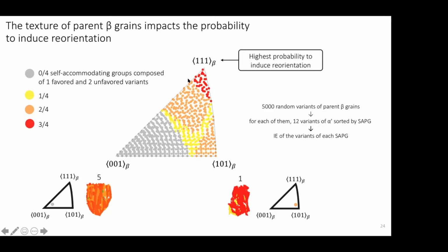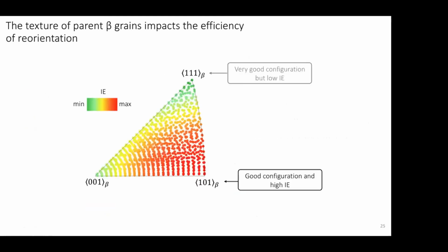So we know now that the occurrence of reorientation depends on the texture of the beta grains. And we know that close to 111, we have the highest probability to induce reorientation, but we also have to take into account another piece of data, which is the value of the interaction energy. Even if we have the highest probability to induce reorientation close to 111, we have in fact a very low value of the interaction energy. And if we have a low interaction energy, as I said, your variant will not give a lot of energy in the tensile direction, so it will not give a lot of deformation in the tensile direction. We can see it a bit like the efficiency of the reorientation. So you have a high probability to have reorientation, but it will not be very efficient. By contrast, next to 101, you have both a high probability to induce reorientation and also a good efficiency. So we think that it is the best compromise to have reorientation.